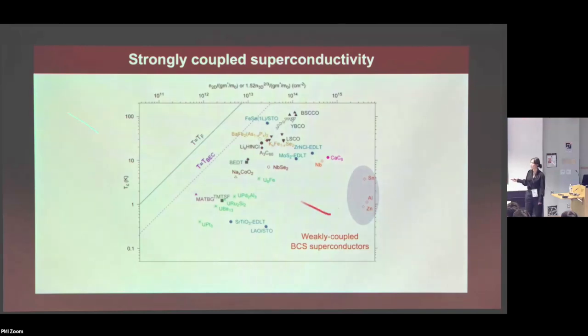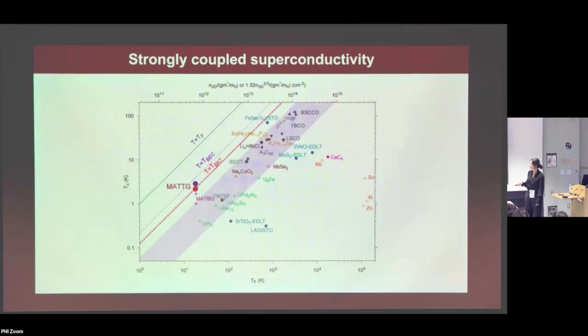And as you move towards the upper left corner, you see this band of different materials consisting of a lot of unconventional high TC superconductors with relatively higher ratio of the TC over TF, okay? And when we try to place our magic angle twisted trilayer graphene, it's right here. So we could see that it's one of the most strongly coupled superconductors.